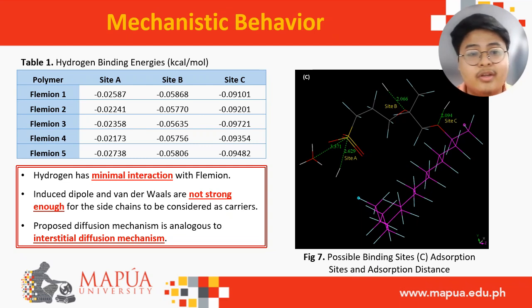Here in figure 1, we can see that hydrogen has minimal interaction with Flemion, with their binding energies being nearly zero. This means that induced dipole and van der Waals are not strong enough for the side chains to be considered as carriers, since for a facilitated transport diffusion, a carrier is necessary. Therefore, our proposed diffusion mechanism for hydrogen in Flemion is analogous to the interstitial diffusion mechanism, wherein the hydrogen is able to diffuse through the polymer matrix due to the small interstices present in the polymer matrix.